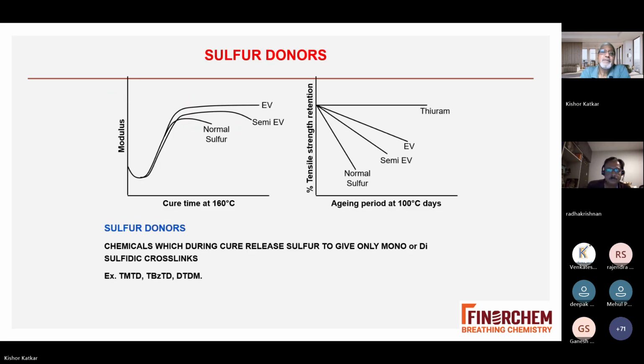Now you can see here the modulus with a normal sulfur, semi-EV and the EV. You can see as your cure time increases, with normal sulfur there is a reversion and modulus will come down. EV gives you a slight plateau, your modulus is maintained, and semi-EV is a compromise between the normal sulfur and EV system. Now you can see that for the same product, if you do the aging, tensile retention versus the aging period at 100 degrees centigrade in days, normal sulfur, even during the aging, the tensile retention is much, much lower. EV is better than normal sulfur and semi-EV, but Thiuram, that is the sulfur donor system, gives even better aging properties at 100 degrees centigrade.